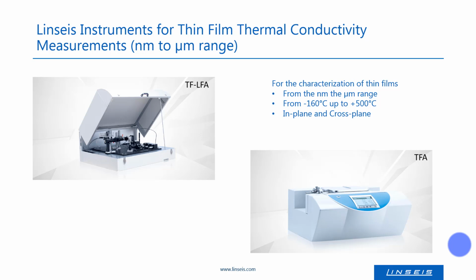Both systems can characterize thin films from the nanometer to the micrometer range and can operate from sub-ambient to elevated temperatures. One important thing to mention is that the TF-LFA measures the thermal transport properties in the cross-plane direction, whereas the TFA measures it in the in-plane direction.